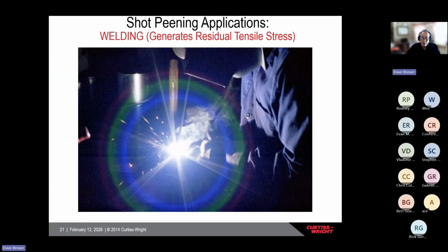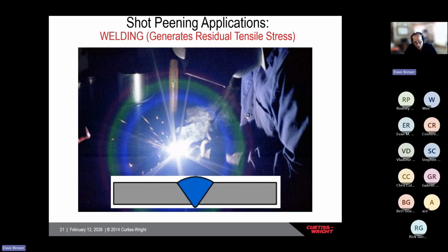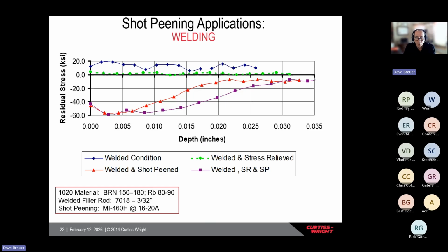Welding is another process that benefits quite a bit from shot peening. The reason is that when you weld something, the weld goes down in its hottest, most expanded state. So the weld wants to cool quickly and shrink as it cools. But since it's bonded to a base material, the base material doesn't let that weld shrink.